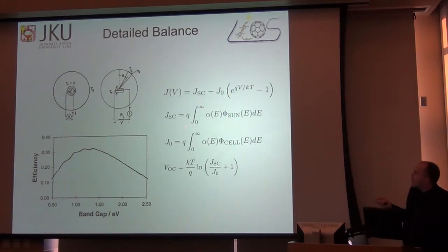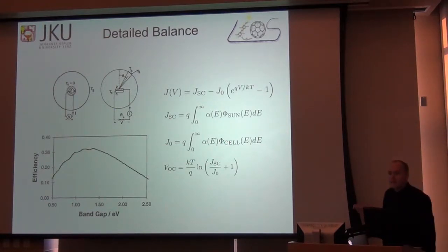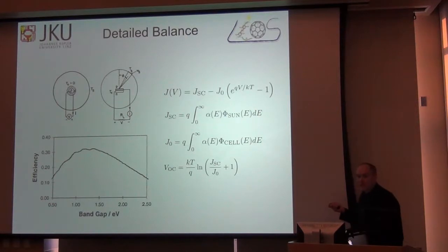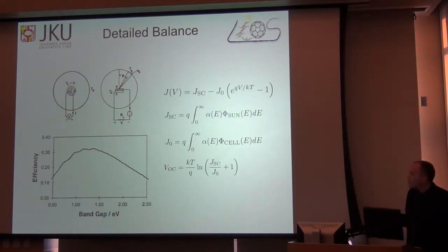And so you wind up with the diode equation. The short circuit current is equal to the absorption of your semiconductor times the flux incident from the sun. But your diode equation has this J0, so your dark current is proportional to that same absorption coefficient times the radiant flux of your blackbody radiator at a given temperature. So the maximum VOC that you can hope to have is limited by the ratio of the short circuit current divided by J0.